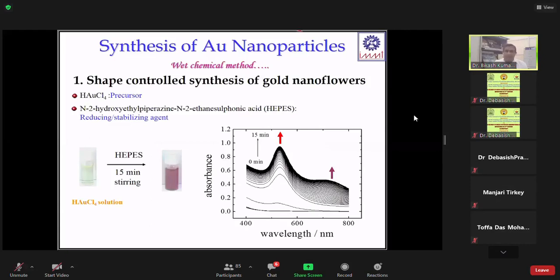So this is a very simple molecule and it is a very good reducing agent, and it can reduce the gold precursors like chloroauric acid, where Au3+ will be there. So you can add HEPES to it with just 15 minutes of stirring. Just take the gold chloride solution, add the HEPES at some optimized concentration, stir for 15 minutes, and you can see gold nanoparticles form, and you can see the color change during the synthesis.